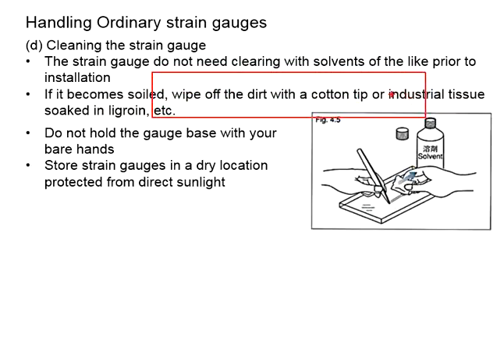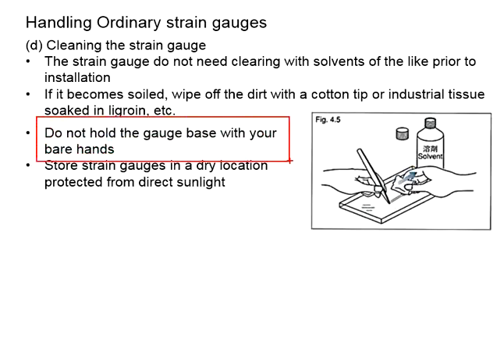While doing this, you need to be very careful. Normally, you don't need to deal with that. Do not hold the gauge base with your bare hands, as this may induce pressure to the gauge base, altering the shape of the gauge base, causing undesired deformations to the sensitive elements of the strain gauge. This may affect the quality of bond between the strain gauge and the test specimen, and also may lead to the damage of the sensitive element, resulting in inaccurate measurements.